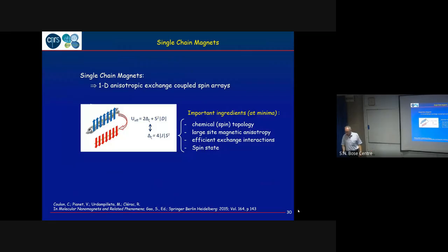Okay, so single chain magnets, which are the goal of this project, are very closely related to single molecule magnets. What we want now in this kind of system is all the magnetic moment aligned in one direction and an energy barrier to go from this situation to this one. But the main difference for the chain system is that in this energy barrier now you have two contributions. You have the contribution I have introduced before that is coming from the anisotropy. But you have also a contribution that is coming from the exchange interaction.